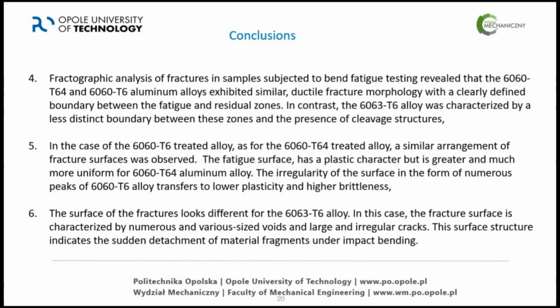The fatigue surface has a plastic character, but is greater and more pronounced for the 6060 T64 aluminum alloy. The irregularity of the surface in the form of numerous peaks for the 6060 T6 alloy points to lower plasticity and higher brittleness. And in the end, the surface of the fracture looks different for the 6063 T6 alloy. In this case, the fracture surface is characterized by numerous voids of various sizes, and large and irregular cracks. The surface structure indicates the sudden detachment of material fragments under impact bending. Thank you for your attention.